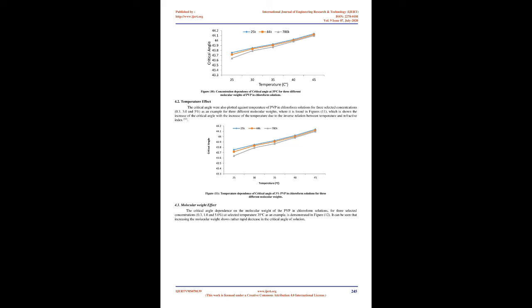2.3 Molecular weight effect. The effect of molecular weight on the reflectivity for each system was plotted against molecular weight for 3 selected concentrations, 0.3, 1.0, and 5.0%, and a selected temperature of 35°C as an example. This is demonstrated in figure 6. It can be seen from this figure that the increase of the molecular weight shows a rather rapid increase in the reflectivity of the solution. This general increase of reflectivity with molecular weight may be due to the increase of polar side groups in the molecular chain of this polymer 29.